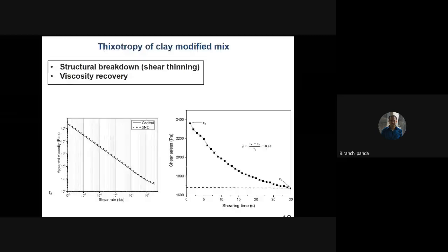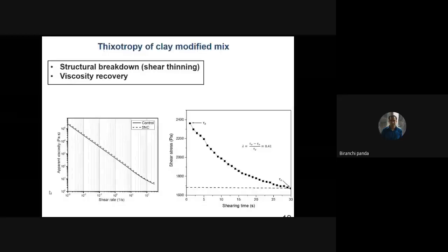So for that, we developed this testing protocol, where we apply a high shear rate and see how fast the material breaks down. From this image, we can see that there is an initial shear stress, and once it completely breaks down, we have the final shear stress. If you take the ratio of these, you will get an index, and this index tells you how fast you can destroy your material. It is important because if you remember the three-stage process, during extrusion we need the material to break down very easily, so that we have to apply low pumping force or low pumping pressure to deliver the material to the nozzle. So this protocol or index helps you select your final mix design, which requires less pressure for extrusion.